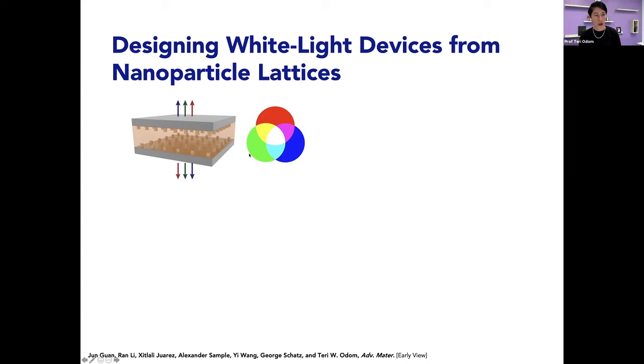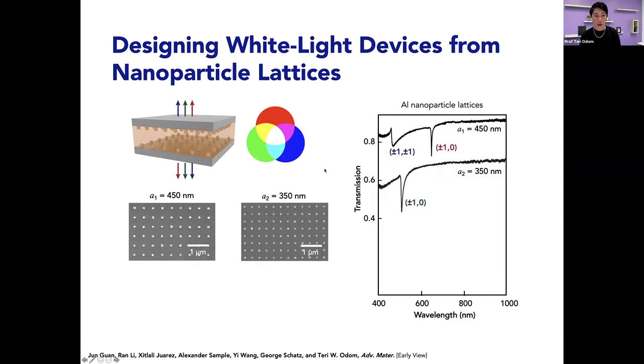And so we designed this sandwich structure of two different lattices that are facing each other. And again, these are aluminum nanoparticle lattices. We focused on a spacing of 450 because the 450 nanometer spacing produces these two modes, very similar to what I showed you earlier. And then we also focused on a lattice that was 350 nanometers because that was able to support an SLR that was in between these other SLR modes.